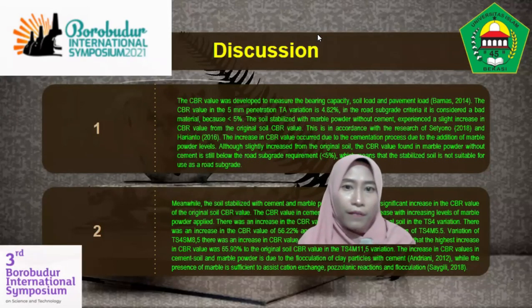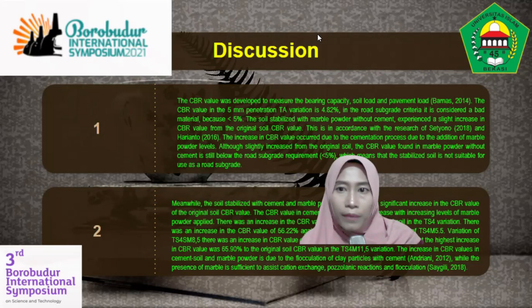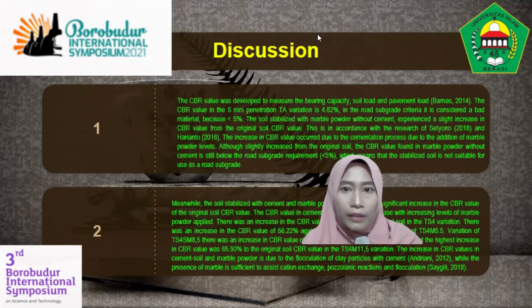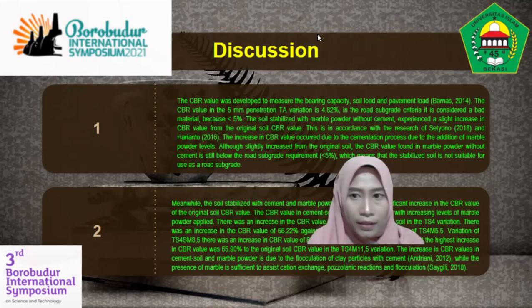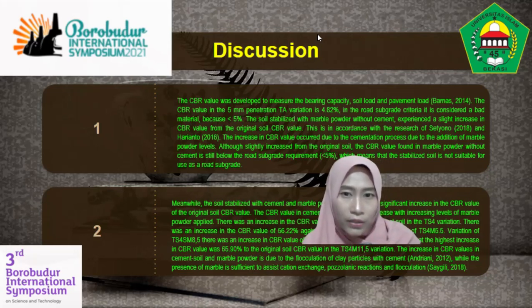Okay, the CBR value was developed to measure the bearing capacity, soil load and pavement load. (Bamas, 2014) states that the CBR value in the 5 millimeter penetration original soil variation is 4.82%. In the road subgrade criteria, it is considered a bad material because it is under 5%. The soil stabilized with marble powder without cement experienced a slight increase in CBR value from the original soil CBR value. This is in accordance with the research of Setyono and Harianto.